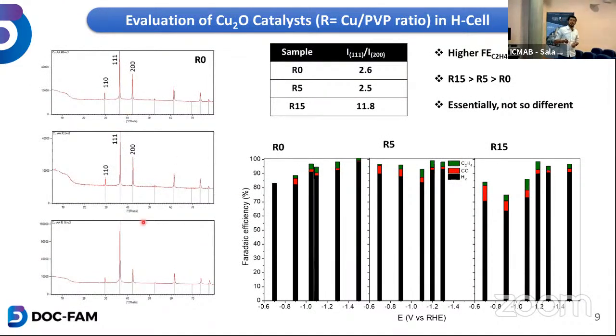When I have taken the XRD analysis, as I showed, the R0, R15. Sorry, this is missing here. This is R0, R5, and R15. So I have 111 planes and 200 planes in all of them. The ratio is better. I can say a better ratio in the R15 ones.